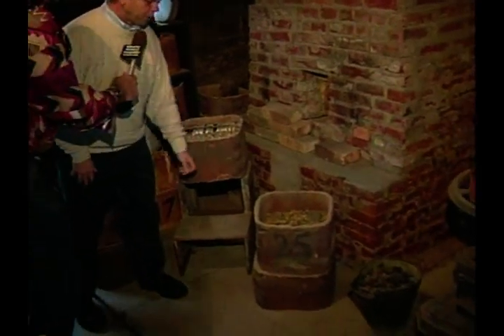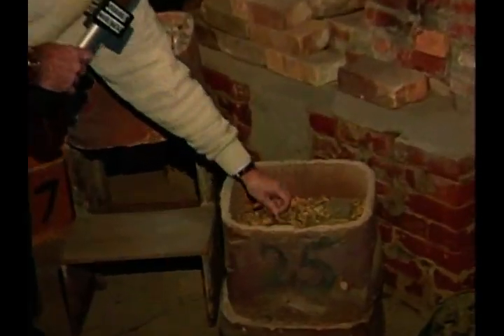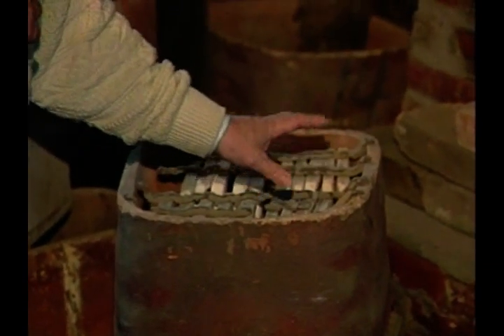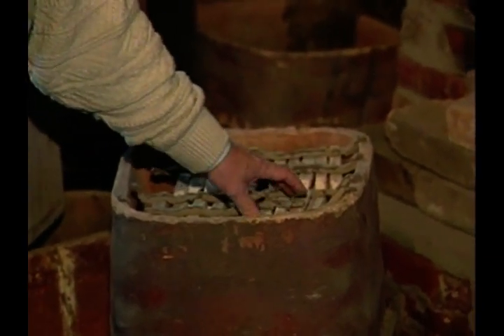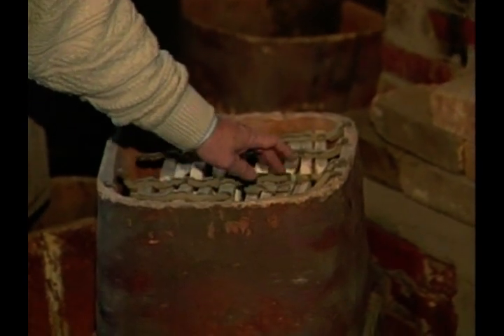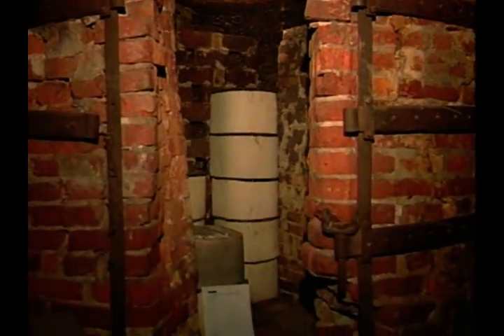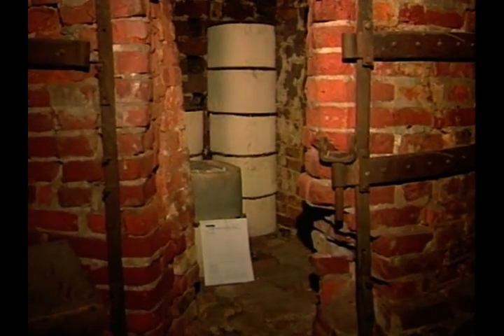Charlie, where are we? We're in the area of the old kilns. This is where all the tiles were fired during Mercer's time. Below us here we have some of the saggers, which were the containers that the tiles were put in before the firing. Down here we have tiles immersed in sawdust and ground coal, which gives a nice oxide color on the firing. And over here we have tiles that are separated with coils of clay, because if the glazed tiles are set face-to-face they'll fuse together, so they have to be held apart. These containers are then put into the kiln for firing. This is the old process, though currently we do use electric and gas kilns.